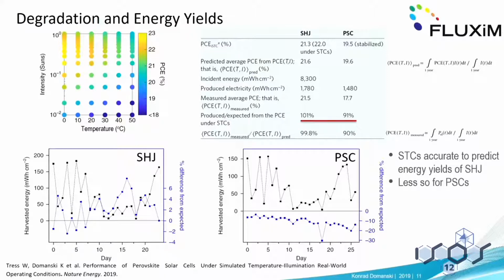So here we see that the standard test conditions are actually a very good predictor of how much energy you can expect from your silicon device, but not so much for perovskite because of the degradation effect. And this is when we compare to the predicted efficiency, which is this one, and we see that we get an even better match for silicon and even worse for perovskite.